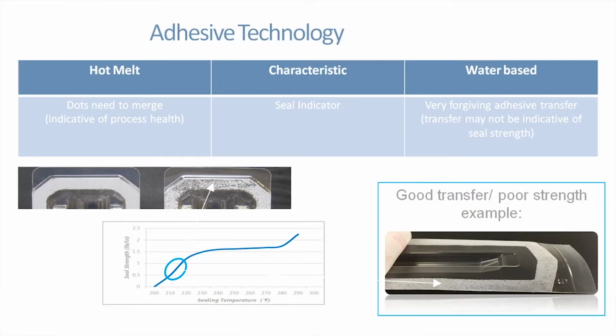Again, it's back to user preference. Some people really like to have the hot melt, because it can be a seal indicator. When the dots are not merged, it means there's something wrong with your sealing process. The water-based can be much more forgiving, and in a sealer that maybe has some issues, you can get a good cosmetic seal more easily with the water-based, but it's a nuance that's slightly different between the two.